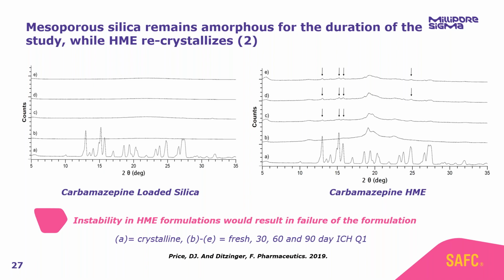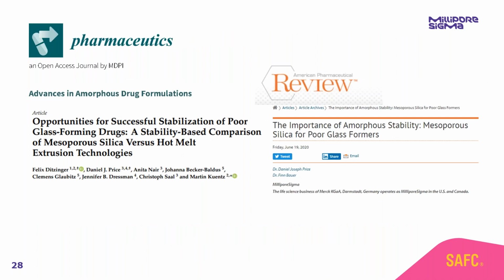Now, we used passive dissolution to show this effect in our study. In the interest of time today, I've not included the passive dissolution data, but if you are interested, I've included the reference to our paper at the bottom, and we have much more data digging into these systems and really looking at what was the impact of this change in solid state on the overall formulation performance. But ultimately, what we saw is that for the hot melt extrusion formulations, our dissolution profile was totally different throughout the study, and at the end of the study, there was no advantage at all. Whereas for the mesoporous silica formulation, we retained a strong, consistent dissolution profile for the duration of our study.